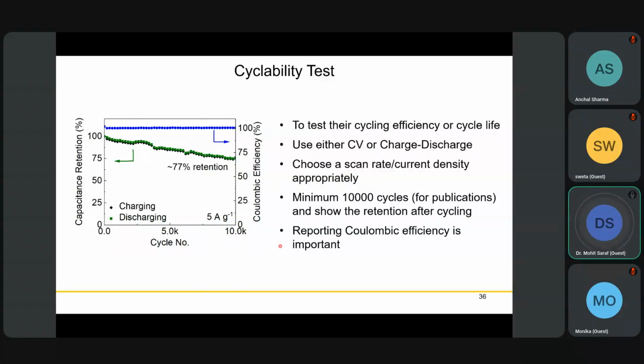It's not like you can choose any random current density, for example 20 ampere per gram, where if the redox reaction was happening at low scan rates, you simply choose a very fast current density or scan rate because you have nothing to lose. In that case you'll get very high performance, nearly 100% retention, but that is not advisable.